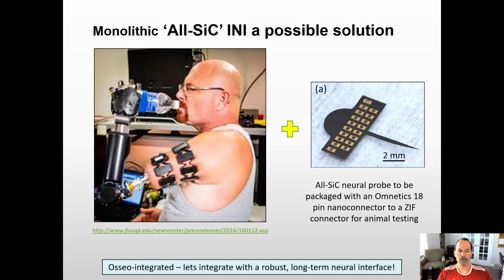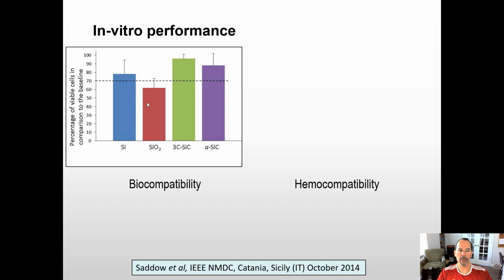So this arm is quite interesting. The fact that it's osseointegrated brings a lot of possibilities to the patient, because they're able to perform all of their life functions with this, including ideally taking a shower. Okay. So what about the in vitro performance? We looked at biocompatibility using ISO 10993, and we see that silicon passes the test over 72 hours, or maybe it was 48 hours, but eventually over a longer time, silicon fails the ISO standard. Oxide fails right from the get-go. Cubic silicon carbide and amorphous do quite well.